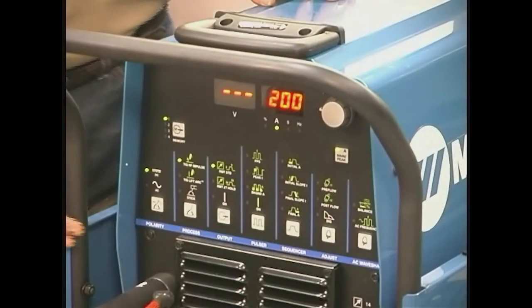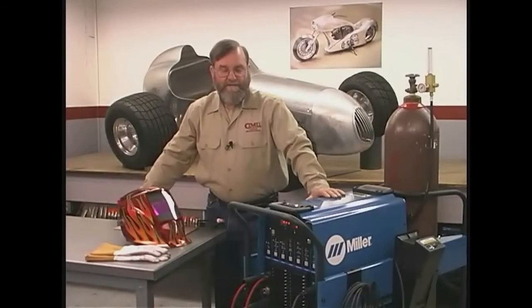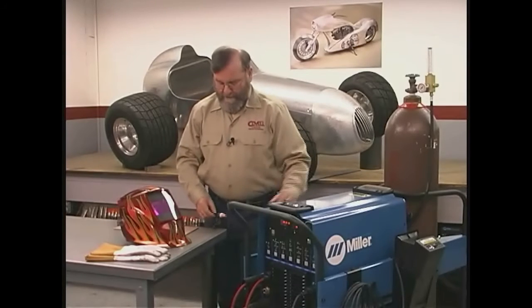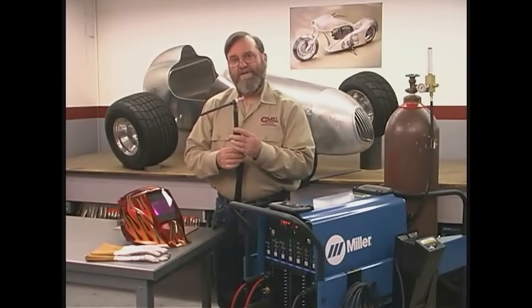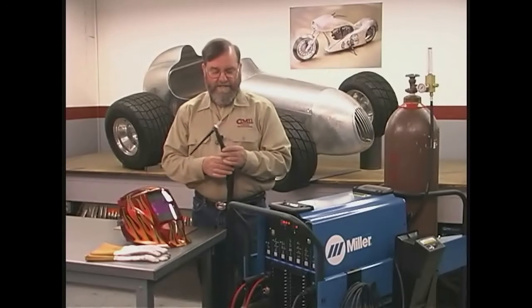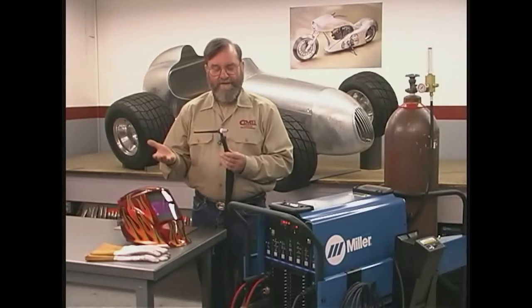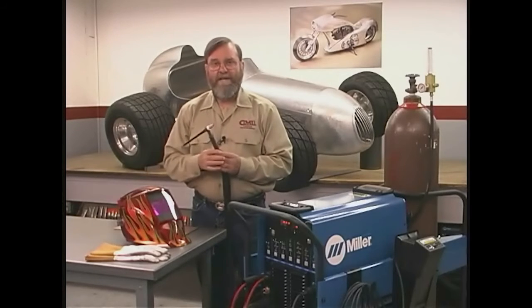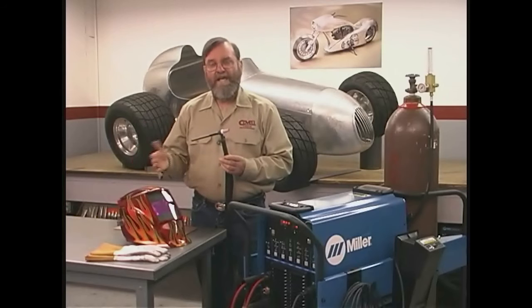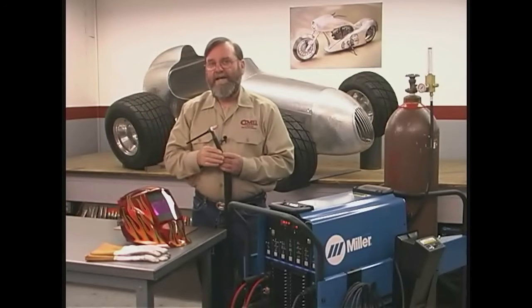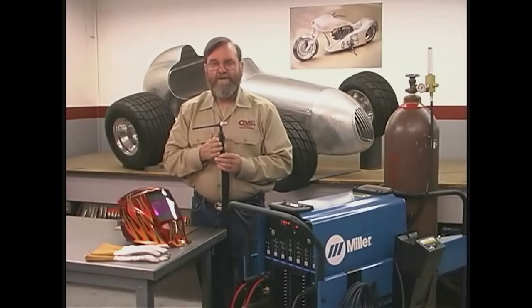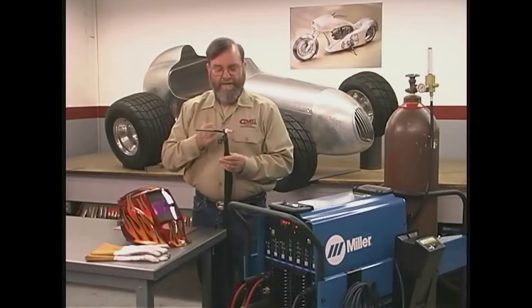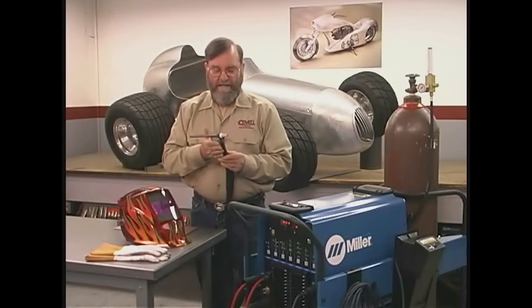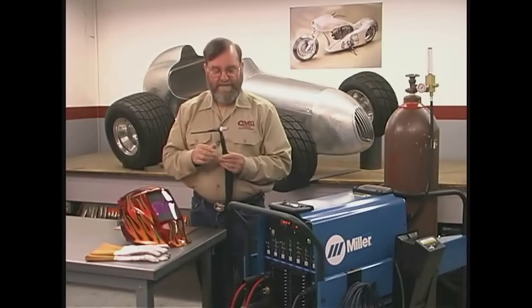The control panel on this machine is nearly identical to the controls on the 200DX. The push buttons control the same factors, they're in the same place, they work the same way. Another difference with this machine is that it's equipped with a water-cooled torch. Now the air-cooled torch is a good unit. It's good for power output around 130, 140, maybe 150 amps for intermittent use. But if you're welding continuously at high amperage rates, the handpiece of the air-cooled torch does tend to build up heat. The water-cooled torch stays much cooler, so that's an advantage for welding thick materials.